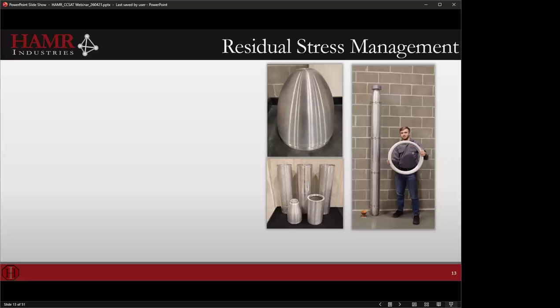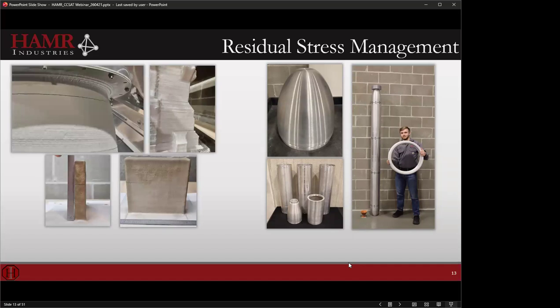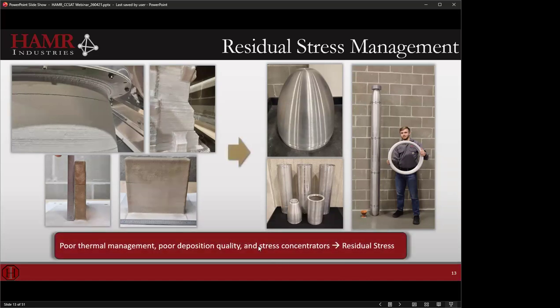And then the part that Jake, who is always the person who ends up taking the pictures, is holding is between 20 and 24 inches. So we can make large parts, and we can do that successfully, and we can manage the stresses. But there are times when we don't manage the stresses or when parts fail. So cracking is a challenge in cold spray, just like it's a challenge in the other modalities. And it's something that we have to address and something that we're working on. And ultimately, we want to take it from the left to the right. So move from geometries and setups that tend to have cracking to setups that don't. And we know that we can because we've done it.